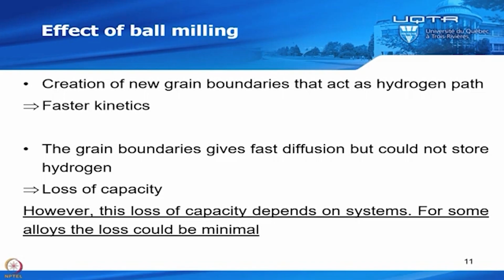But I have to say that this loss of capacity depends on the system. So for some alloys, this loss could be minimal because when you hydrogenate, dehydrogenate, you may recreate a coherency. Okay, so your crystallite size may increase a little bit because the hydrogen will force the unit cell that is on the grain boundary to get coherent with the unit cell beside it. So this loss of capacity with the grain boundary is not true for all systems, okay? But for some systems, we see that it scales very well.